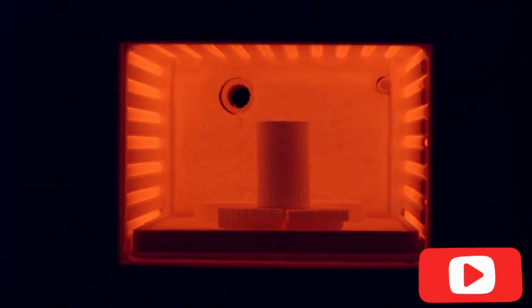Using the speed process, we now place the muffle on a honeycomb sagger tray in the furnace at 850 degrees Celsius. Do not preheat the investment plunger and pellets. After 45 minutes, the 100-gram muffle can be pressed.